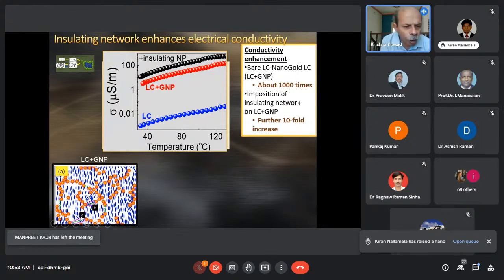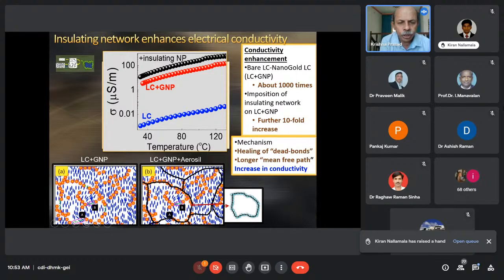And what you have are, for example, in these situations, an insulating network which gets formed, which are the black lines here, over and above that of the gold nanoparticles. And because of this insulating network that forms, the gold nanoparticles are frozen in space, because nematic is a liquid, and therefore thermal fluctuations play a large role in them.